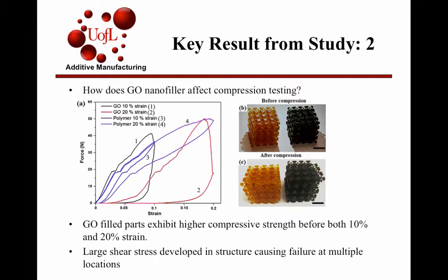I think they made some conjectures as to why they failed so early, or failed, period. I think it was because when you have the graphene oxide embedded throughout the structure, it allows a lot more stress to be placed on the polymer molecules that are surrounding that structure, and then less stress on the ones around it. So that takes away from the entire compressive strain of the molecule.